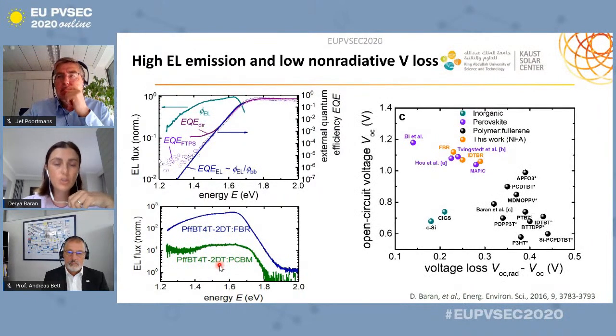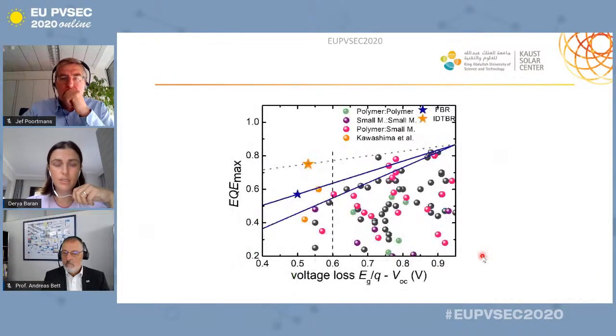And with that, we could calculate the voltage losses, or non-radiative losses, you could say, and compare it even to different technologies. So here you can see the fluorine derivatives with polymers and CIGS and silicon. And as you know, they are limited on the open circuit voltage. And here are some of the perovskite manuscripts at that time. And here non-fluorine acceptors are quite exciting because we could get really good open circuit voltages with extremely low voltage losses. And coming back to the graph I showed you now, we were able to reduce this voltage loss and keep the EQE as high as possible. And following this work over the years, now I think there are data points where you can see EQEs up to 90% and also lower voltage losses.